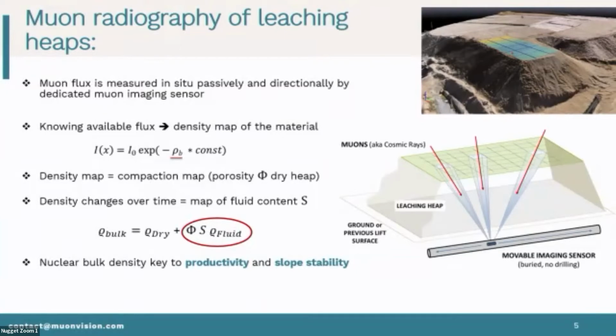Now, a density map, if you think of a dry heap or an initial stage, is essentially the compaction map, because density in this case is not really the grain density, but the combination of density and porosity. By the same token, if you look at this density map over time, and you look at the volumetric equation, you understand that if you have a change in density, you either have compacted it more, which is something you can see from the outside, or you have added material in the pore space of the heap, which is what we do every day. In this case, it's a liquid, which displaces air, that creates a density change over time. Knowing what the porosity is, I may assume it, I may need to measure it, and knowing what the density is, I'll be able to determine the saturation. In other words, in absolute terms, you can express this in detail.